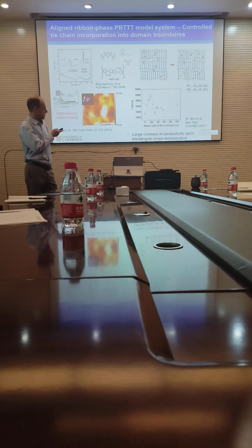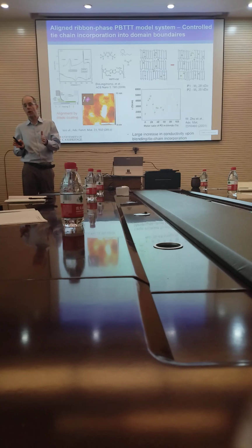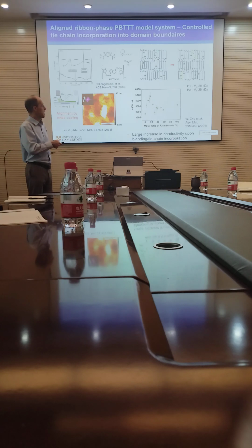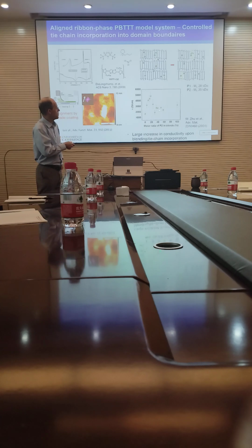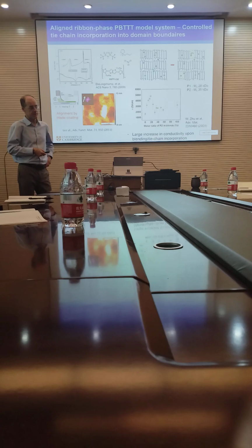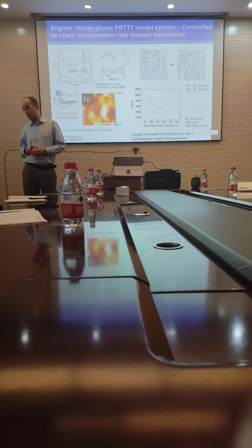So you can see here the electrical conductivity as a function of the blend ratio. So 0% is just the low molecular weight polymer. 100% is just the high molecular weight polymer. And in between you have different blend ratios. And what you can see is that the low molecular weight polymer on its own has a conductivity of 1,500 Siemens per centimeter. And then when we add a little bit of the high molecular weight polymer, the conductivity jumps up to 5,000 Siemens per centimeter. And then if you add too much, it goes down and it settles off at around 3,000 Siemens per centimeter. So that's pretty much exactly what we had expected.